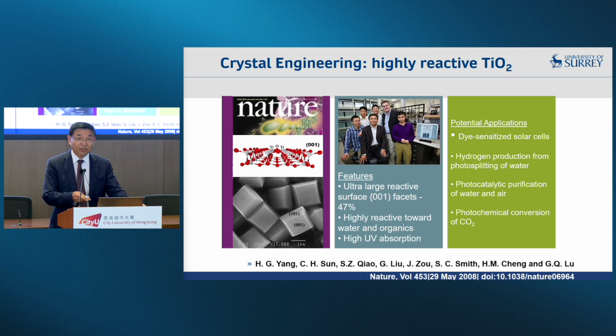So experimentally, using hydrothermal synthesis and fluoride doping, we are able to preferentially grow this 001 facet and to have a stable 001 facet, even after heating, to the tune of 47%.